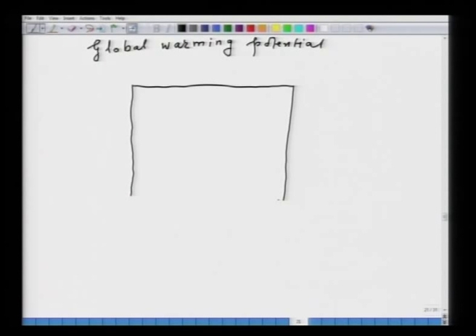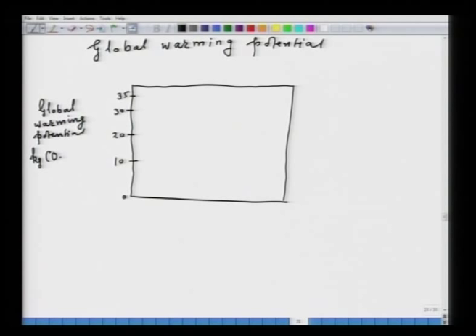This one, so let us say 0, 10, 20, 30, and let me take somewhere here 35, and this is global warming potential evaluated in terms of kilogram CO2 equivalent per kg metal. So again you see titanium has a very high environmental impact. This is for the titanium. Now, if we take again aluminium, this is for the aluminium.